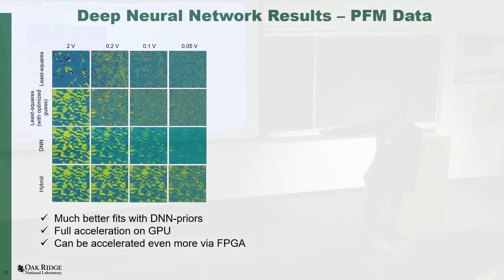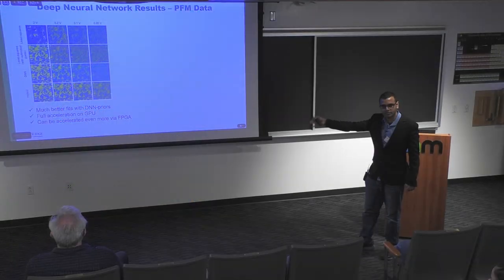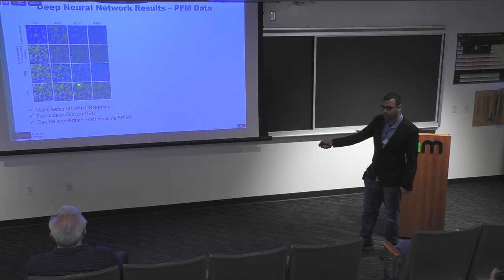And you can see that as I go from 2 volts to 50 millivolts, using just the standard least squares method, there's a lot of noise once you get to 50 millivolts. On the other hand, if I use deep neural networks without any other optimization, then you get relatively good results. But actually, the best results come from a hybrid method where we use the deep neural network as the prior. So we pass our data through the deep neural net, it gives us the prior, and then we use that as a starting point for the LM algorithm to give us the optimum for that particular point.